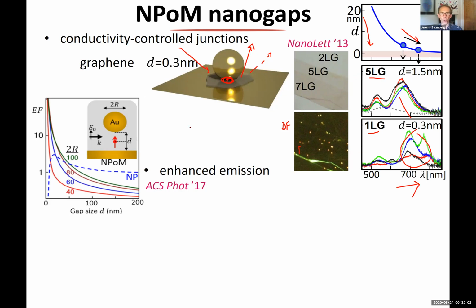One of the interesting things is normally in plasmonics, if I bring an emitter close to a gold surface, then when I get very close, within about 5 nanometers, what I get is quenching. So if I look at the light that's coming out from some sort of emitter in the gap, it gets quenched because it preferentially gets absorbed in the gold. In the nanoparticle mirror situation, that's not what happens, because there's a competition between absorption of light in the gold and radiation out. And because this is a very, very efficient waveguide, the re-radiation out wins. So the efficiency actually gets better as you go to smaller gaps.